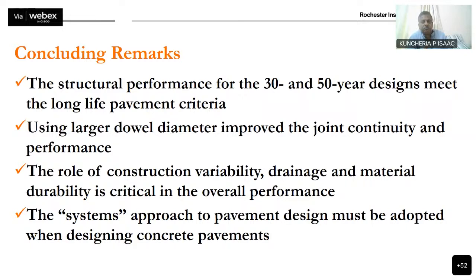Well, not really. Because remember, if you increase the thickness of the slab, you might increase the temperature gradient. So the way you counter environmental effects is through the spacing of the joints. You can shorten the joint spacing and reduce the curling stresses, because the curling stresses are directly related to the thermal gradient in a concrete pavement. So you increase thickness if you need, but there are other ways to improve structural integrity. Thickness is not the only way.